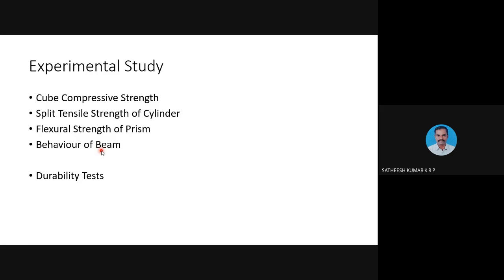And in all these studies, we observed that for the cube compressive strength, here I will also explain the method which we used to arrive at the composition. We used Hardjito and Rangan's recommendation, which was given in 2005. From the density of the concrete, we arrived at the volume of aggregate. From the volume of aggregates, we got the volume of the rest of the components. The ratio between the hydroxide solution and the silicate solution, we kept as 1.5. To say it in the form of a mix ratio, the ratio between fly ash, alkaline solution, fine aggregate, and coarse aggregate which we used is 1:0.45:1.75:4. Yes, we were using a large volume of coarse aggregate in our study.